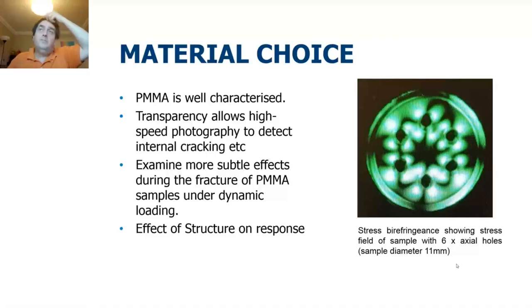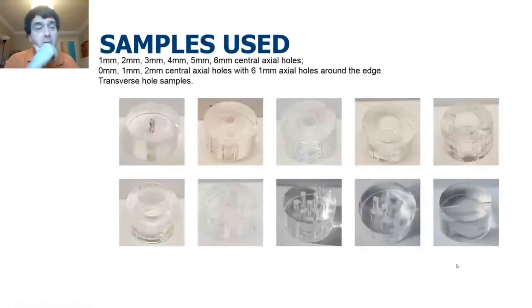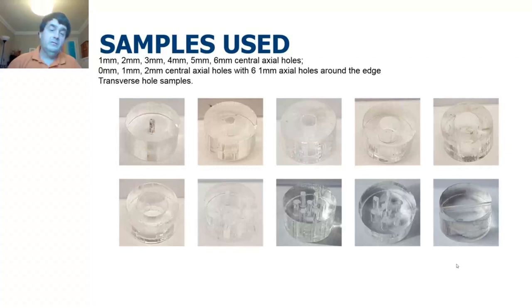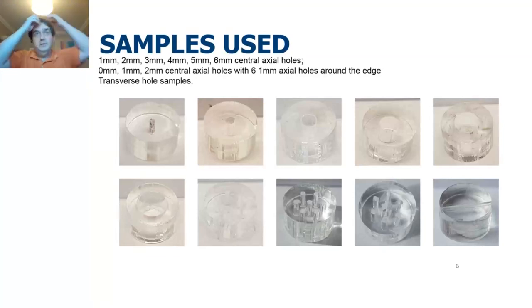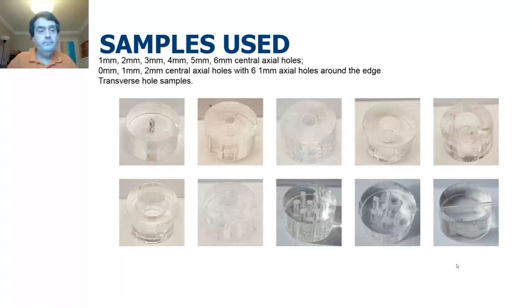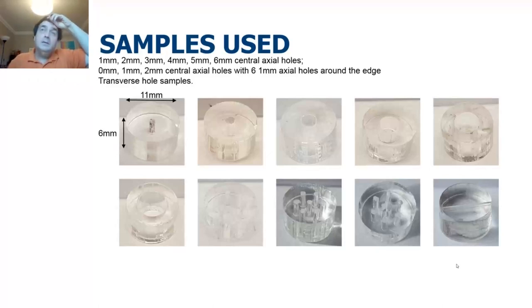We can look at the effect of changing the structure on the response of the material. The aim is not just to look at induced damage in the form of cracks; we can also look at damage in terms of voids in the system. We had a number of samples — all Perspex discs — and we drilled holes of different diameters into the material. We drilled multiple holes, and finally a hole from the side. We then put the system in the Hopkinson bar as a controlled loading system.